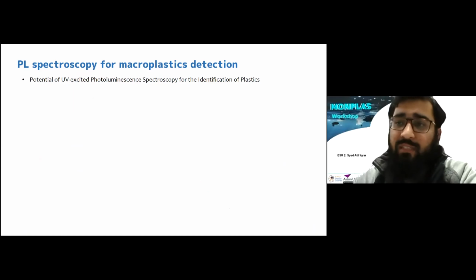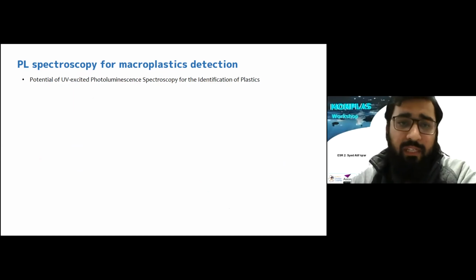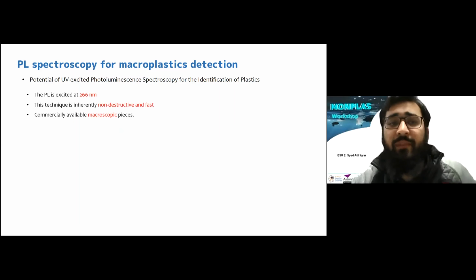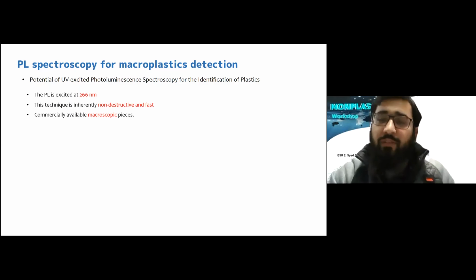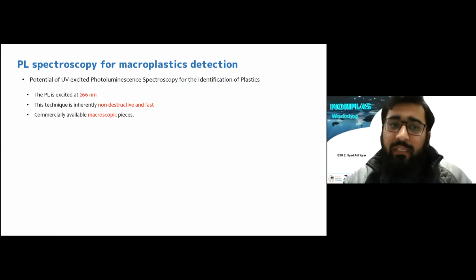And also the same group published another paper recently in 2021, and this time they used an excitation wavelength of 266 nanometer, and they also claim that it is a non-destructive and fast technique, and they used commercially available macroplastics. The problem with this technique is that we are not sure about the resolution of this technique, and we are still trying to explore whether photoluminescence can be a replaceable technique for detection of plastics or not.